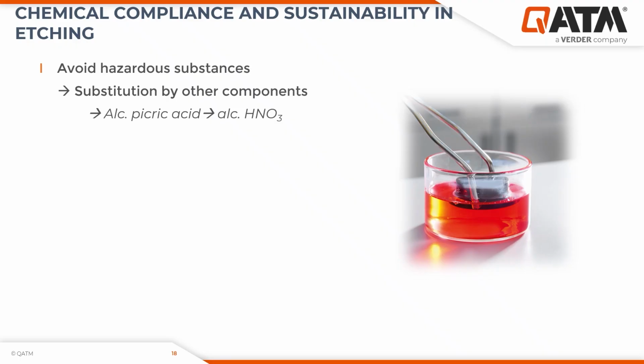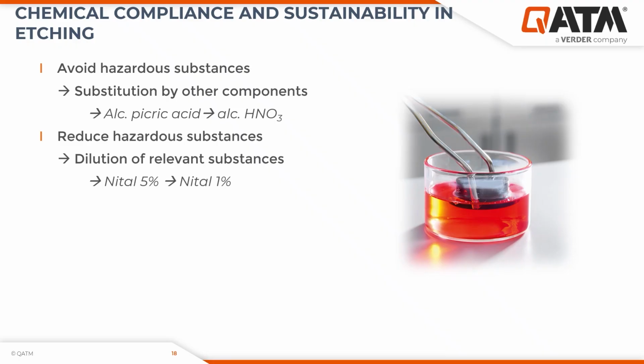Second, you can try to reduce the amount of hazardous substances. So basically, if you are not able to completely avoid them, you can try to dilute your etching agent to a less dangerous level. We have here an example, in this case alcoholic nitric acid, 5 weight percentage, which shows similar, or depending on the material you're trying to etch, similar etching properties and etching profile compared to less concentrated, more diluted alcoholic nitric acid etching agents, in this case 1 weight percentage, if you're willing to increase, for example, the etching time, or slightly increase the temperature of the etching agent in order to increase the reaction or etching speed.